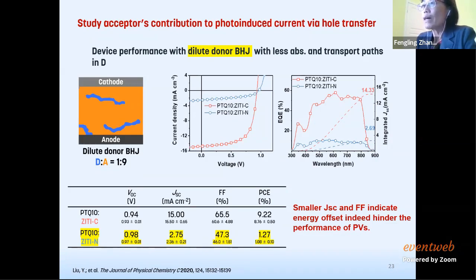This way we use 1 to 10. We only put 10% donor there. You can see from the device image that mostly the orange part, which represents the acceptor, is there, so the donor is merged into the acceptor. We hope this way we can decrease the impact from the donor and only get the information from the acceptor. Indeed, for this non-optimized stoichiometry, the efficiency of the device decreases. For this one, the device performance drops from 13 to 9, and for the ZITI-N it drops from 7 to 1.3. The fill factor clearly dropped much, and the current is also very significantly smaller.